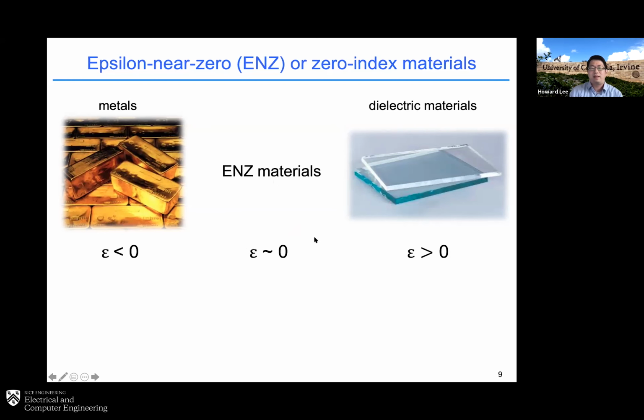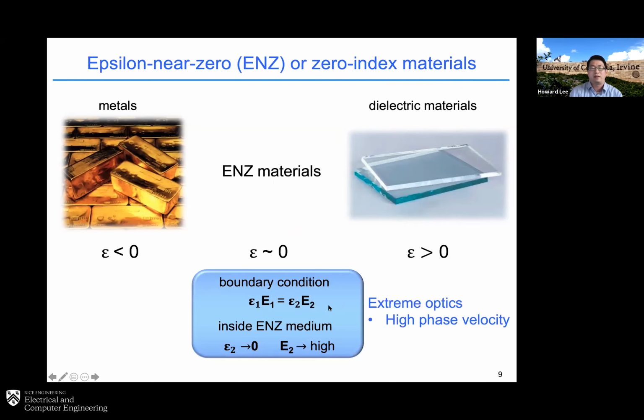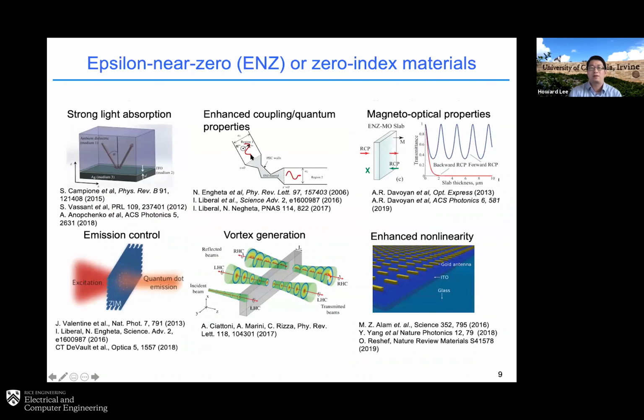And in this ENZ regime, you can find there are a lot of extreme optics you can discover. For example, if you just take a simple boundary condition, if your epsilon is close to zero, your electric field can be enhanced significantly. At the same time, if your epsilon is close to zero, your refractive index is close to zero, and your phase velocity can increase a lot as well. That's why you can see a lot of really interesting physics and optics in this so-called ENZ regime. And that's why in the last couple of years, there have been a lot of exciting demonstrations of applications and properties in this kind of ENZ material. For example, making perfect absorption using ENZ material, controlling coupling or quantum properties, enhancing the magneto-optical effect, enhancing emission, controlling emission, even vortex generation, or quite excitingly, a lot of enhancement of the nonlinearity using ENZ material as well.